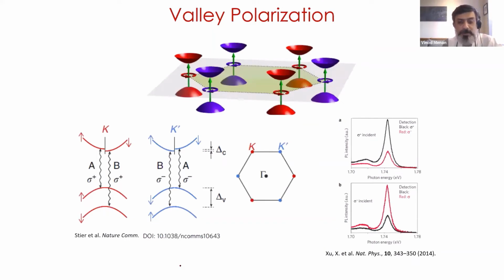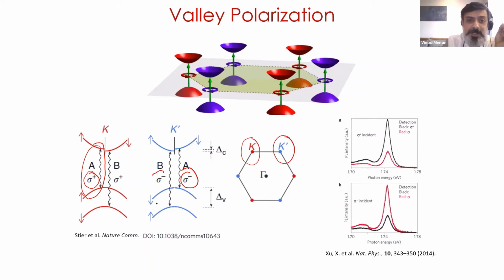I briefly alluded to the topic of valley polarization. So I'm just going to tell you what it is. It comes from the fact that in these systems, there is a broken inversion symmetry. And so the K and K prime points in your crystal lattice, in momentum space, are not identical. And so the selection rules of the light are different because of the spin of the carriers that are involved. So if you look here, there are two different transitions. So you have the K for the two different excitons. Let's just focus on the A exciton for a second. You see the A exciton can be excited by sigma plus, whereas here the A exciton can be excited with sigma minus because of the spin of the carriers that are involved. Okay, so here it's spin up, here it's spin down, and so you can get excited with sigma plus or sigma minus light.